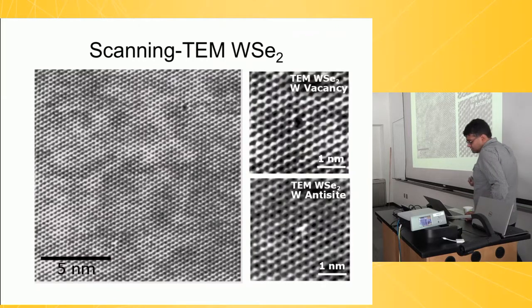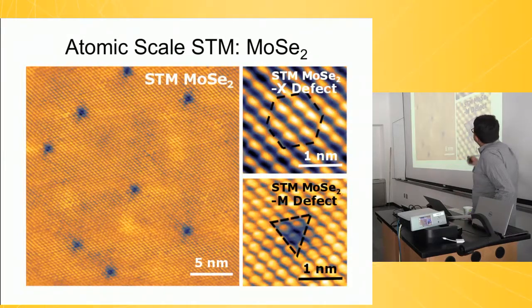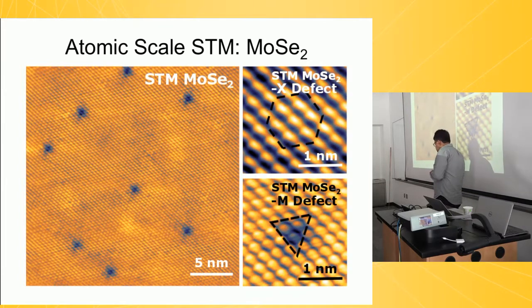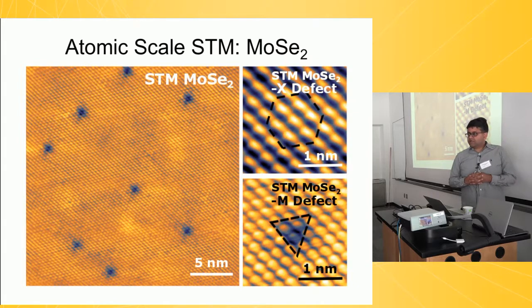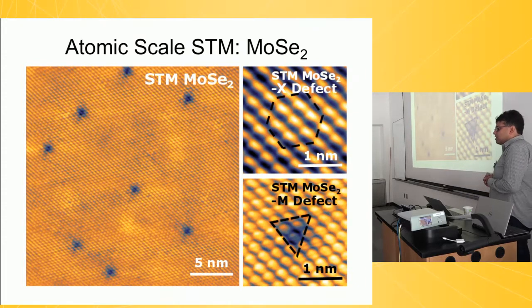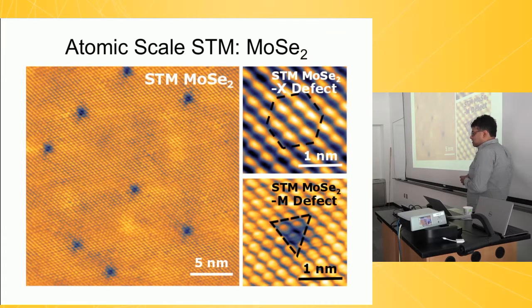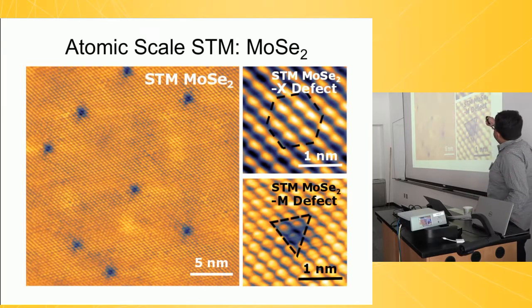Now, the anti-site is somewhat trickier to see in TEM, at least with the TEMs that we have. What we know from STM is that we don't have a missing chalcogen atom here. We don't have a chalcogen vacancy. In fact, if you read the TMD literature, everybody talks about chalcogen vacancies. In our two years of scanning these things a million times, we've probably seen three chalcogen vacancies. There aren't any chalcogen vacancies. But these things are a defect on the chalcogen site.